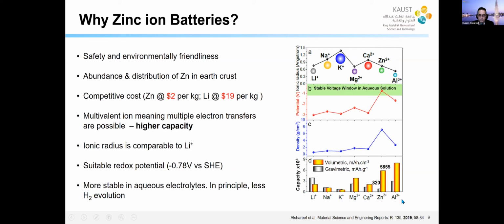Just the oxidation of aluminum. Aluminum forms oxides much more easily than zinc, and that oxide has a band gap of 7 eV, which is extremely insulating. So you actually don't need a lot of oxide on the surface of aluminum to kill your device and degrade its performance by a lot. So that is the reason.